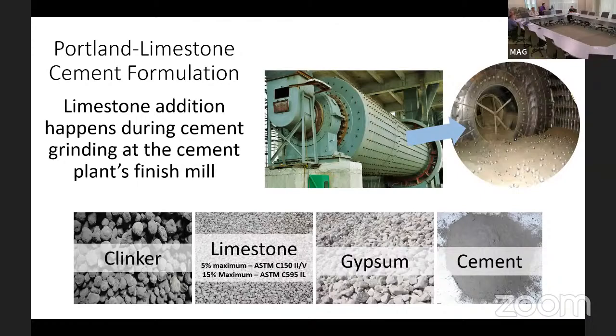So the clinker is the product that comes out of a kiln. You put raw feed that's been targeted for calcium, iron, silica, and alumina. You put that into a high burning kiln at 3,000 degrees Fahrenheit.